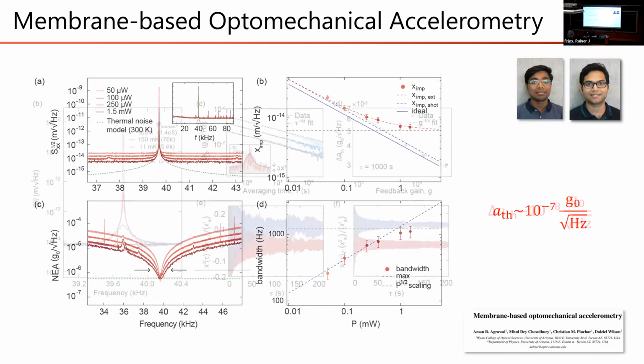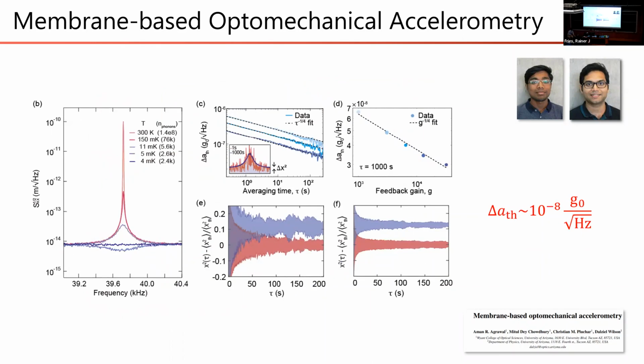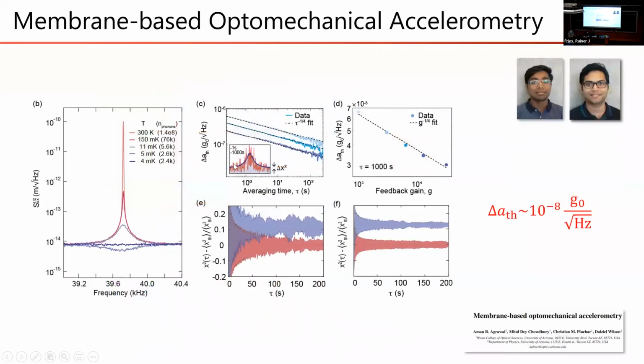And it turns out that this technique of laser cooling is actually useful for measuring incoherent forces, in this case, incoherent inertial forces. What you really care about when you're measuring a weak incoherent force is the signal-to-noise ratio. To improve it, you basically want to average over a larger band, and you can effectively do that by cold damping. So we can decrease the time it takes to average down this noise to a nominal level using feedback cooling. Doing that, we've achieved 10 nanoG sensitivity at 40 kilohertz.